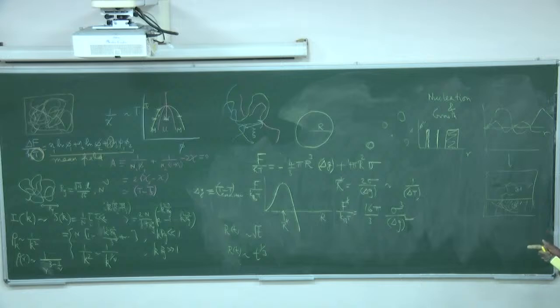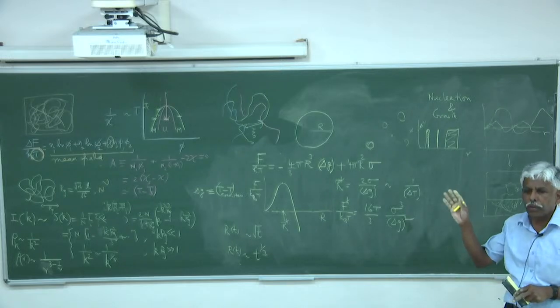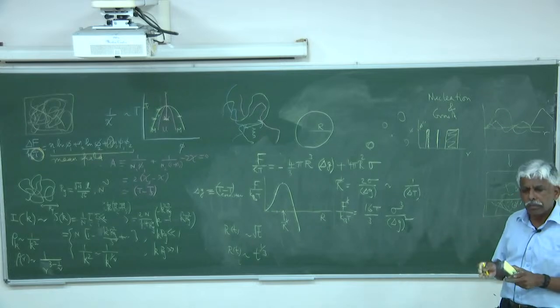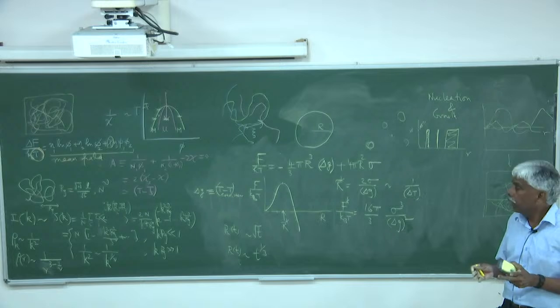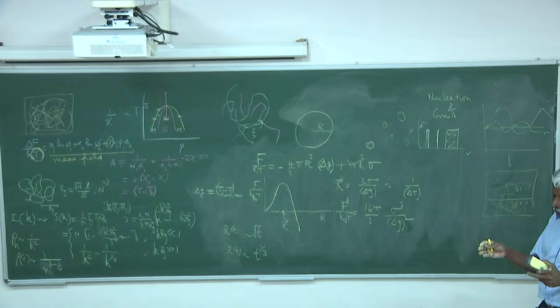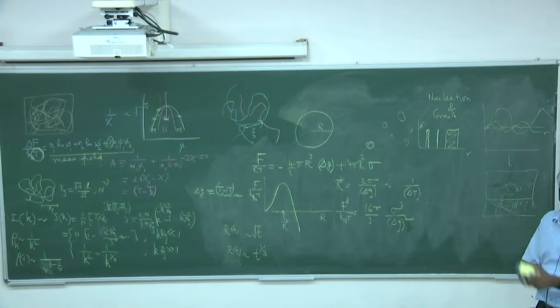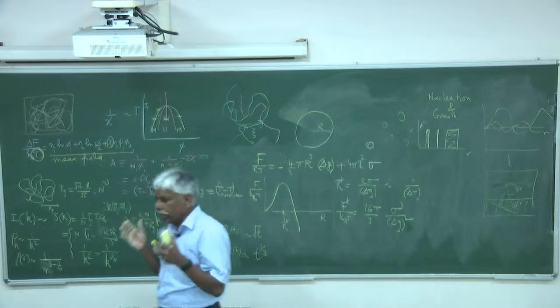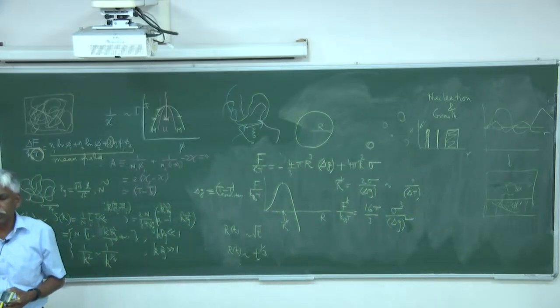One thing I did not point out here is, in the last lecture I told you, if you have a charged system, even in equilibrium, we have spontaneous selection of structure, microphase separation, we talked about it. In a similar way, when you look at the kinetics, you have a cutoff of wave vectors. In the case of a simple system with macrophase separation, all wavelengths larger than a certain value will grow. Here, the large wavelength fluctuations would not grow, and short wavelength fluctuations would not grow. Only the wavelengths corresponding to the microphase-separated structures will grow with time, and they get locked into that structure forever.